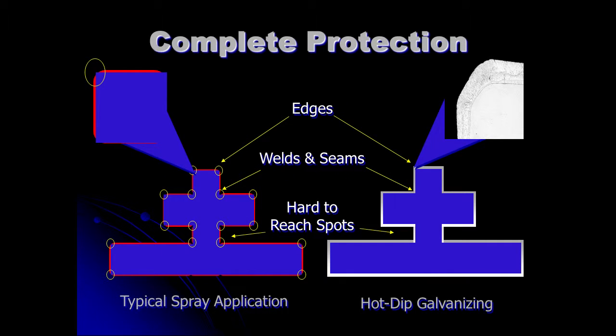Edges. Because we grow the coating and then freeze it, this sharp edge has the same amount of zinc as this flat surface. And anytime you paint or metallize, you have human error in there. With hot-dip galvanizing, it's a dip process, so it's more of a uniform coating because we go down in the zinc and then we come out.